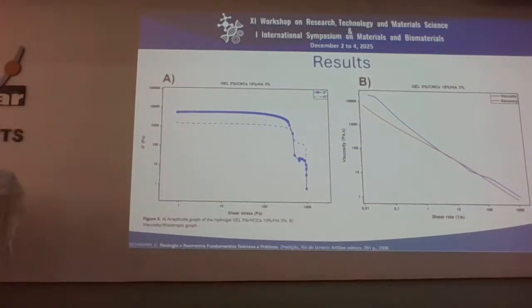So using the factorial design results, I was able to establish the ideal formulation of my hydrogel, and the subsequent rheological tests confirmed that the hydrogel has the characteristics of a printable material. For example, gel-like behavior, which means the hydrogel maintains an elastic response over low to moderate shear stress until the shear stress becomes strong enough to disrupt it. And a shear-thinning and thixotropic profile. In other words, the viscosity of the hydrogel decreases with increasing shear rate, but the hydrogel has the capability to increase its viscosity again.